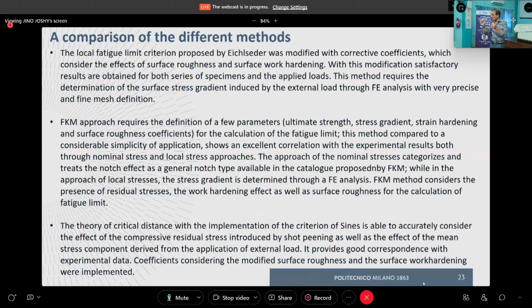Indeed, I was forgetting that to apply the different methods, we have to modify some of them. The local fatigue limit proposed by the German author Eichlseder was modified with a corrective coefficient because it was not taking care of the surface roughness and surface work hardening. By means of this coefficient, the agreement was satisfactory. Okay. And we also did some finite element analysis to consider the surface stress gradient.